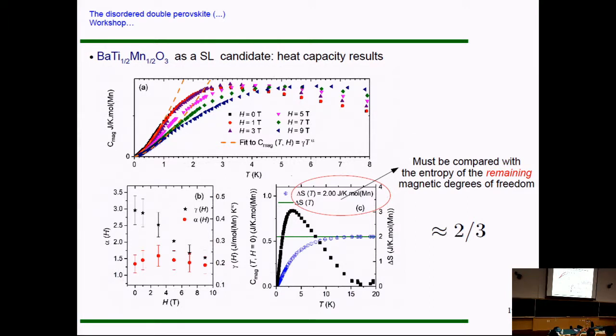And this gamma factor here, even if you consider the error bar, is decreasing as you increase the field. And if you accept the idea that you have some sort of dynamic magnetism here, it can be understood as: as you increase the field, you quench the fluctuations, and then you decrease the contribution to the heat capacity.